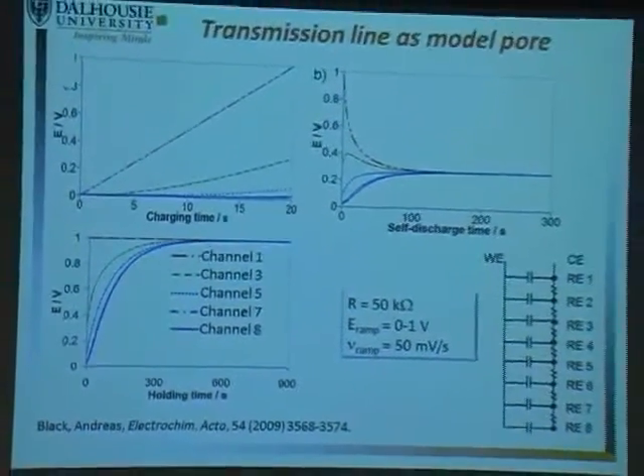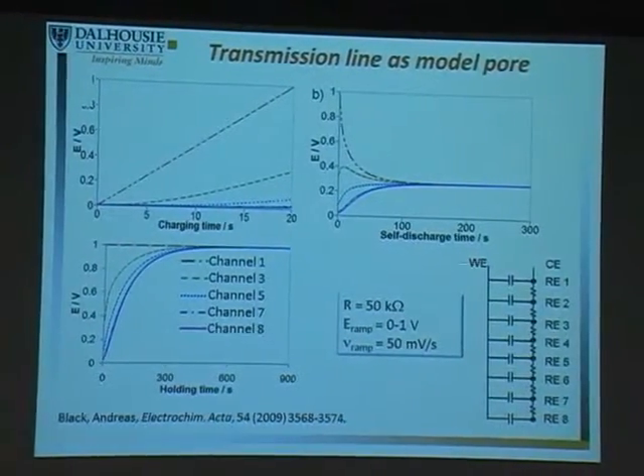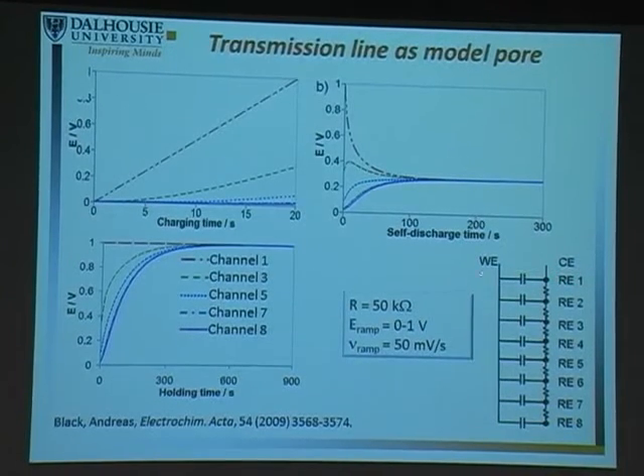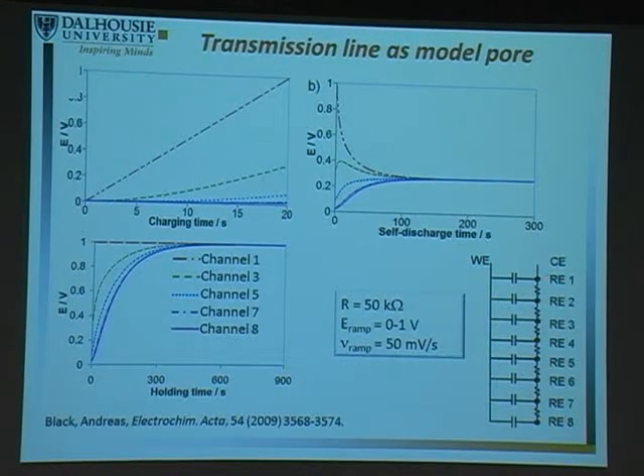And so we built this simple transmission line. The resistors that you see here model your solution resistance. The capacitors model your pore wall. The tip of the pore is up here, and the base of the pore is down here. And so we then looked at this model as if it was a pore. We can charge the tip of the pore, so capacitor 1 up here. This is a reference electrode 1. So we're measuring the potential between our working electrode and reference electrode 1. And we're controlling that, and we're charging it, and the rest of the pore acts exactly the way we would expect a pore to react. The capacitors lower down, deeper into our model pore, charge much more slowly. Then, if we immediately open the circuit, which we can do in B, we would see that potential equalize.